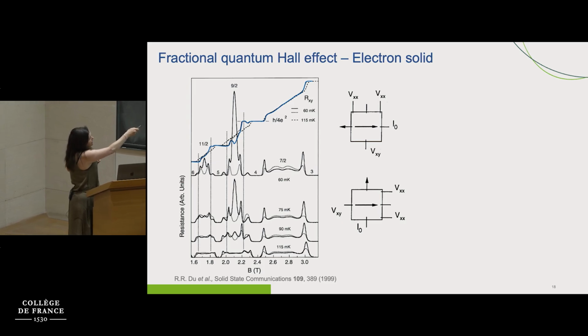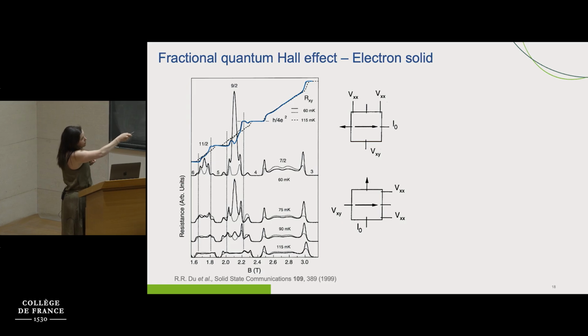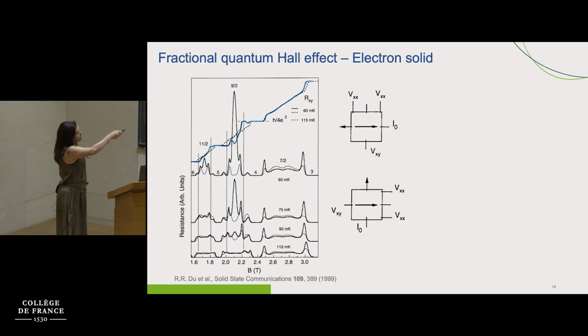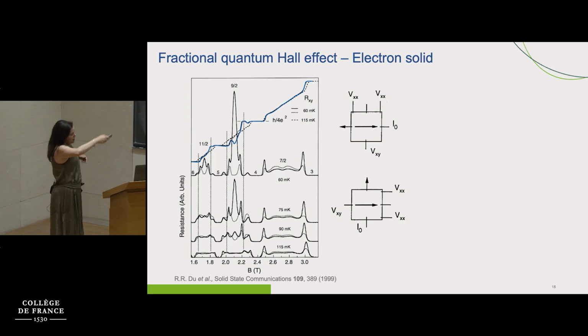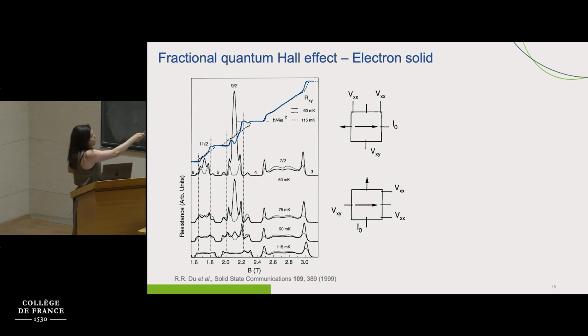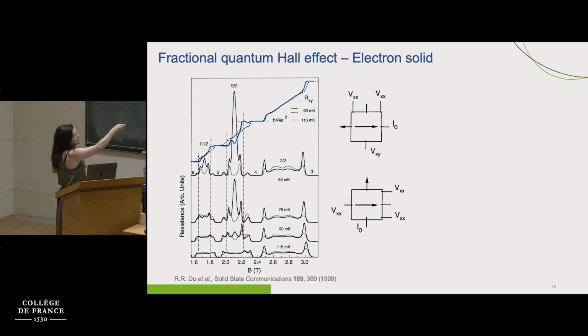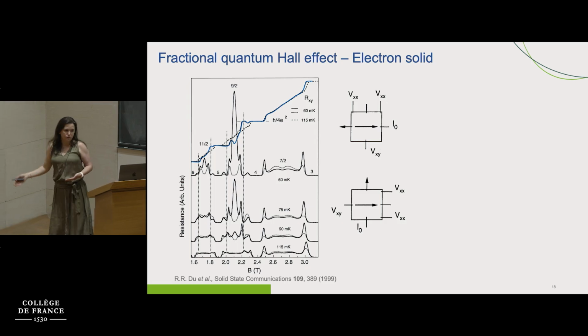So you can see here that if I measure this in this configuration, where I'm applying the current like this and measure it here, this is the crystalline orientation, this arrow, okay? So the crystalline orientation is going to stay the same. I'm going to change whether I measure parallel to this crystalline orientation or perpendicularly to it. You're going to see that especially around the even denominators, the longitudinal resistance is strongly anisotropic, okay? And the Hall resistance in both cases will go back from the fractional states that were there before to a quantized plateau of the integer quantum Hall effect, okay?